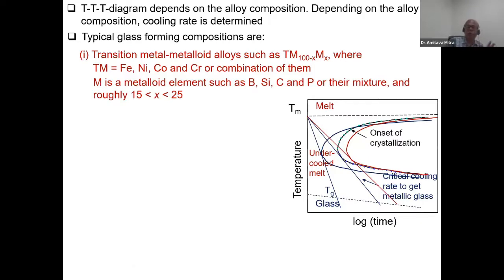I cannot go for any practical purpose with pure iron in amorphous phase by this technique, because in that case the pure iron TTT curve's nose will come in such a position that the cooling rate we cannot go that fast. So we require some metalloid or other element for alloy formation so that the TTT curve can be shifted towards the right hand side.